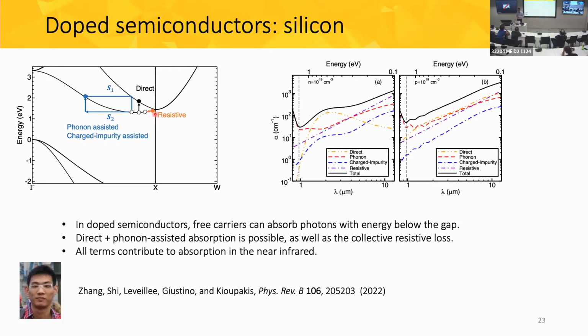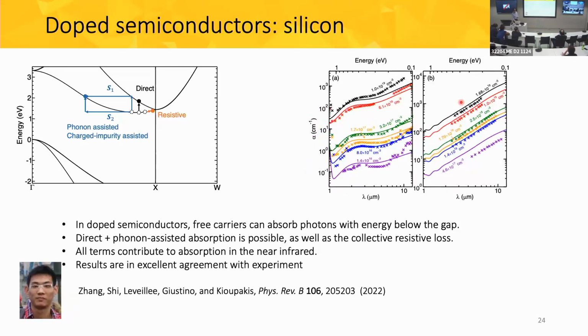So we factor in all these terms, the direct, the phonon-assisted, the resistive term, as well as scattering by impurities. And we found that all of the contributions are similarly important, both in N-type silicon and in P-type silicon. And if we sum them all together, we get the solid blue lines that you see here that include the contributions by all of the terms. And next, when compared to experiment, we find that indeed we're in very good agreement to experiment over a whole range of wavelengths and doping concentrations. And in particular, we reproduce these shoulder-like features here that comes with a direct transition from the bottom to the next conduction band.